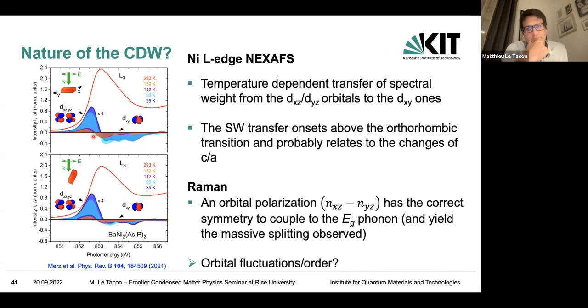So it's already present possibly in the tetragonal phase or wherever the CDW forms. On the other hand, one mentioned that a good candidate in the Raman scattering to couple with the Eg phonon was an object which has the B1g symmetry. And it turns out an object that has the B1g symmetry is an orbital polarization, which would be the orbital occupation difference between the xz and the yz orbital. And so altogether, I think, this suggests that the charge density wave we are dealing with here has a strong orbital character, so it's probably orbitally polarized.